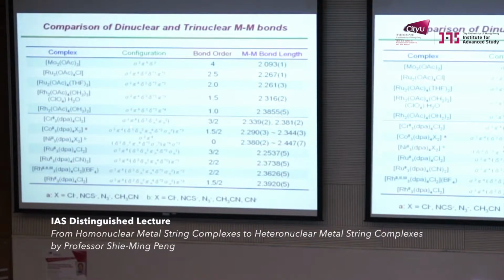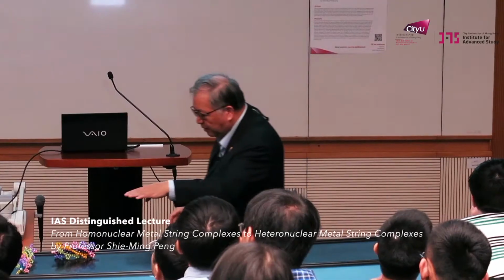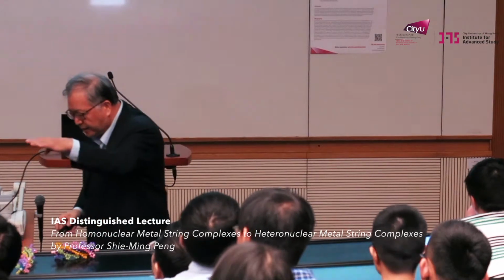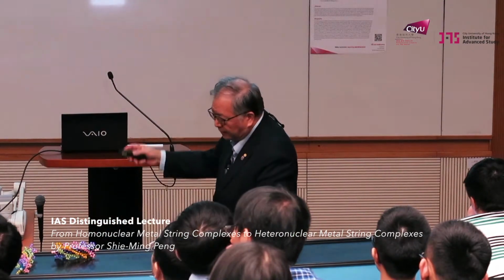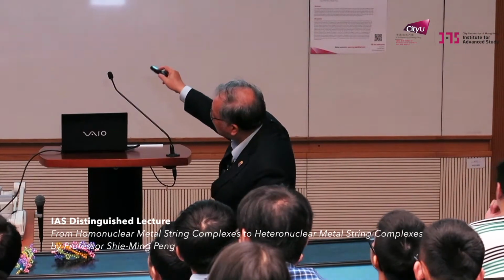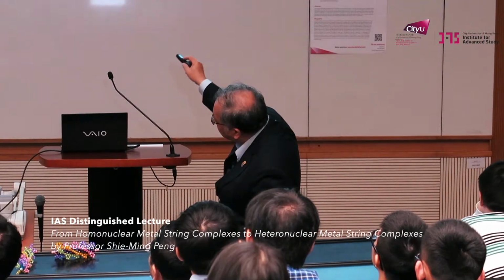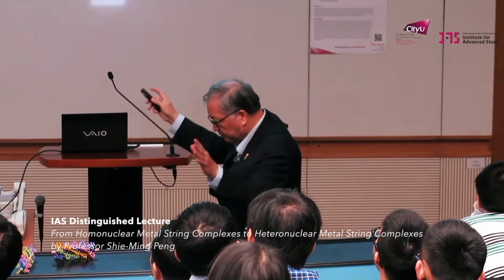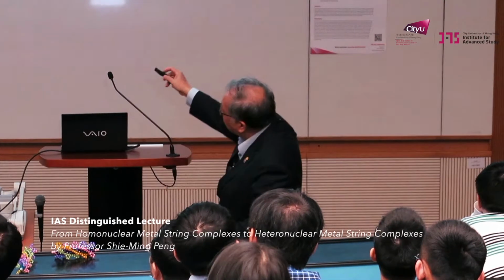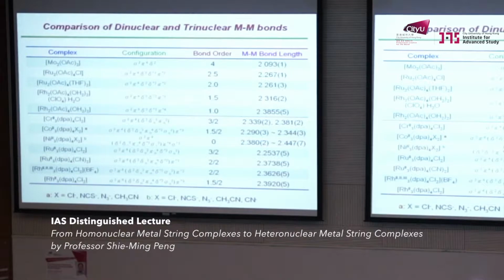For dinuclear metal-metal bonding, you have 1 sigma bonding orbital, 2 pi bonding, 1 delta bonding. So Cotton discovered this metal-metal quadruple bond with 2.09 54 years ago. And you can see here the bond order from 4 to 1 for dinuclear metal-metal bonding. And here I already gave you all the explanation about the electronic structure, the bond length, and also the magnetic property.